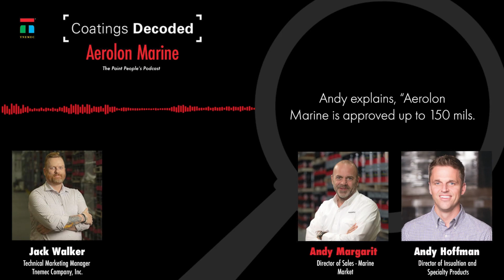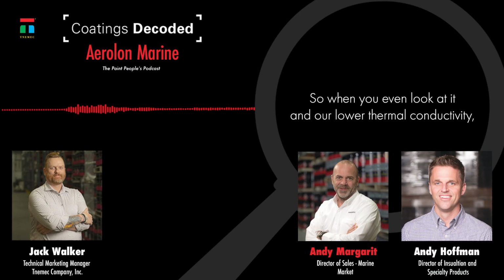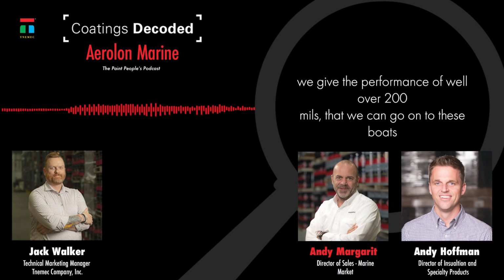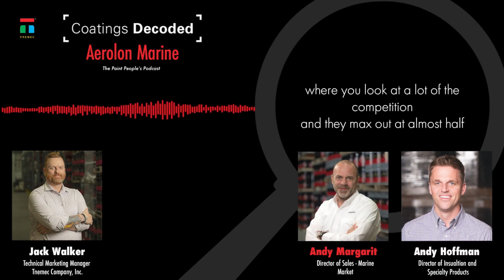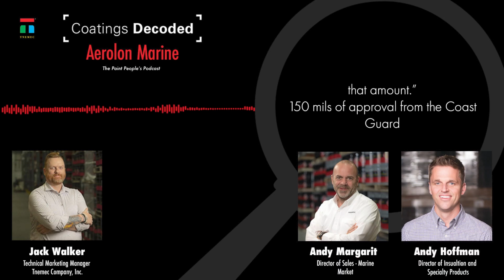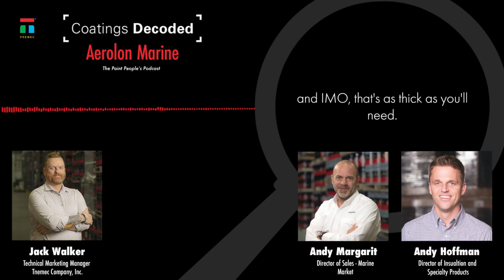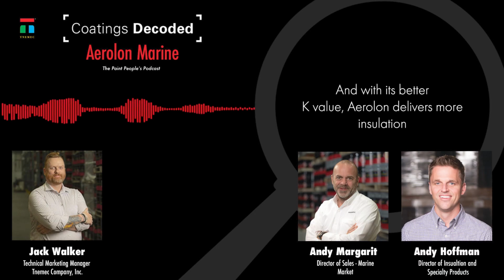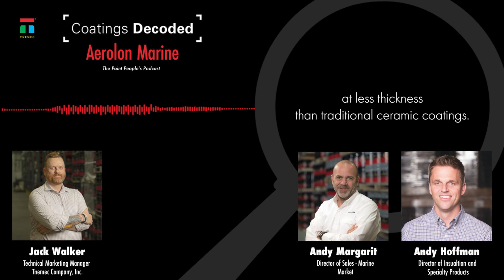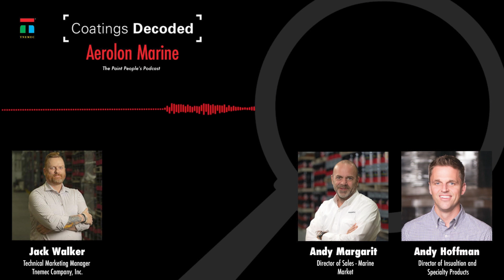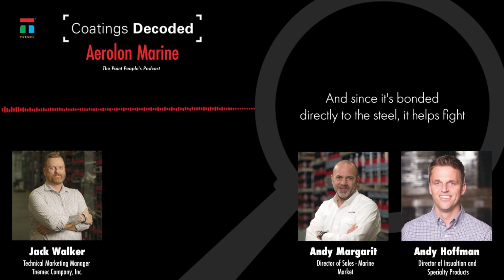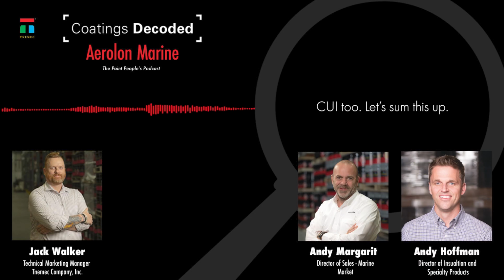Aerolon Marine is approved up to 150 mils. So when you even look at it at our lower thermal conductivity, we give the performance of well over 200 mils that we can go onto these boats. Where you look at a lot of the competition, they max out at almost half that amount. 150 mils of approval from the Coast Guard and IMO. That's as thick as you'll need. And with its better K value, Aerolon delivers more insulation at less thickness than traditional ceramic coatings. And since it's bonded directly to the steel, it helps fight CUI too.